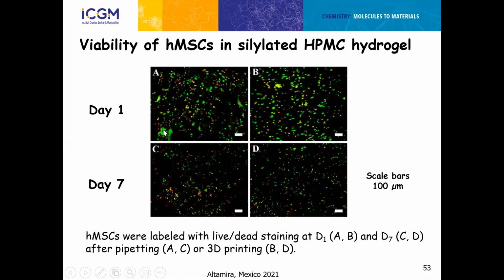It's okay. In both cases, after 1 day or 7 days, it's very similar. It's about 60 and 65. It's not so high, I know that it's not so high. We suspect the cytotoxicity comes from traces of organic solvent remaining in the starting precursor. And there is no difference between pipetting of cells or introducing cells by 3D printing.